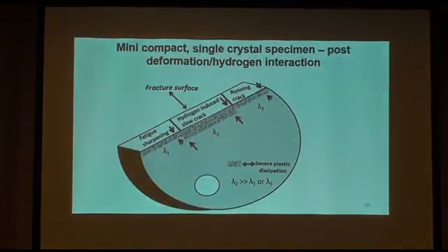And here we see, and by this I'll finish, you see the specimen itself, as I mentioned before. The beginning is a region of fatigue sharpening. Then I have hydrogen-induced cracks, and then it's a running crack. And what you see here is the amount of plasticity that is involved in terms of dissipation on the cleavage plane.